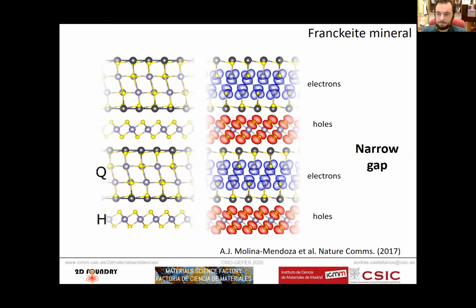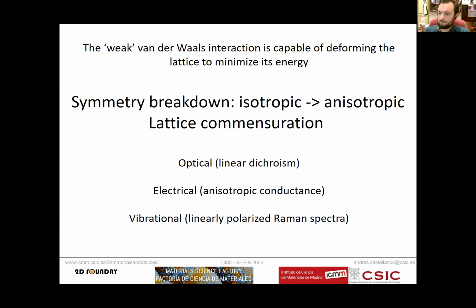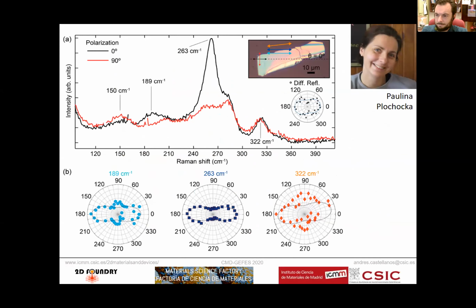Another question: when you do the polarized Raman measurements, you were seeing this modulation with the polarization, right? Were you able to identify the symmetry group from these measurements, and if so, does it match the symmetry that you expect for the crystal itself? I think not. If I remember correctly, all these peaks are attributed to really weird vibrations of the lattice, but these are hand-waving arguments. In the literature you can find these peaks attributed to some vibrations, but simply because they resemble the Raman mode of galena, the lead sulfide mineral, and therefore we believe there is a vibration of the lead atoms against the sulfur atoms. But it's not clear what Raman modes they are. All are hand-waving arguments so far. Okay. Yeah.